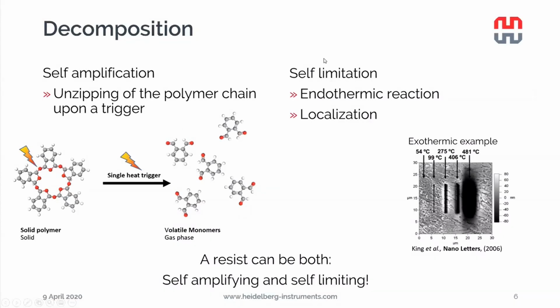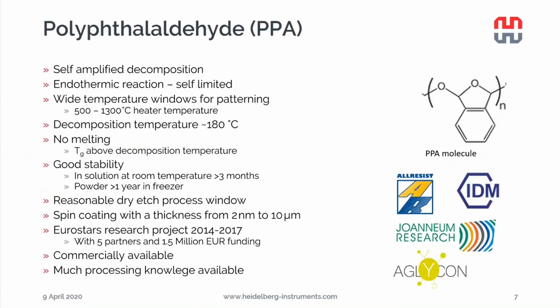So what we would like in a resist is a self-amplification and a self-limitation by being endothermic. And such a resist actually exists. That's the polyphthalaldehyde that we also recommend to use for the NanoFrazor. It is self-amplifying across this carbon-oxygen bond backbone of the polymer chain, and the whole unzipping reaction is endothermic. We can use a wide temperature window for patterning from 500 to 1300 degrees heater temperature.